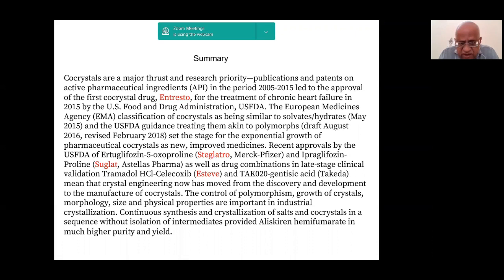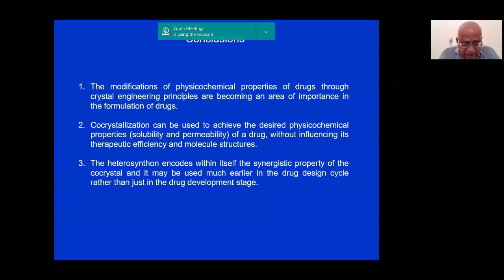India, with a strong generic pharmaceutical industry, must take advantage of co-crystal technology and crystal engineering. To summarize: modifications of physicochemical properties of drugs through crystal engineering principles are becoming important in drug formulation. Co-crystallization can be used to achieve desired physicochemical properties — solubility and permeability — without influencing therapeutic efficiency and molecular structure; in fact, it can even improve therapeutic efficiency. The trimethoprim-nitrofurantoin heterosynthon encodes within itself the synergistic property of the co-crystal and may be used much earlier in the drug design cycle rather than just in the drug development stage.